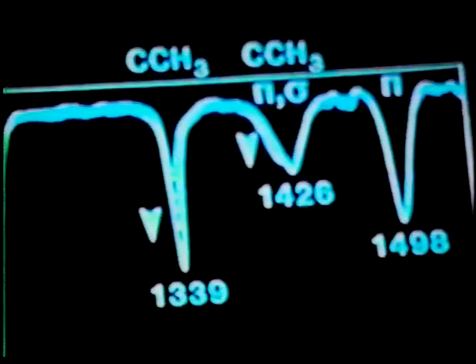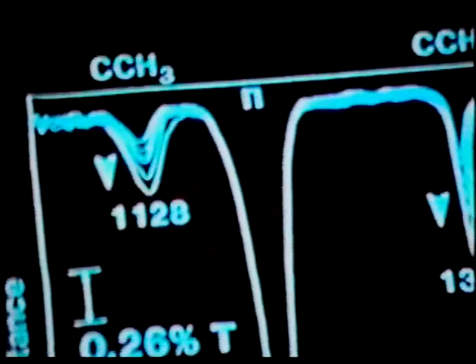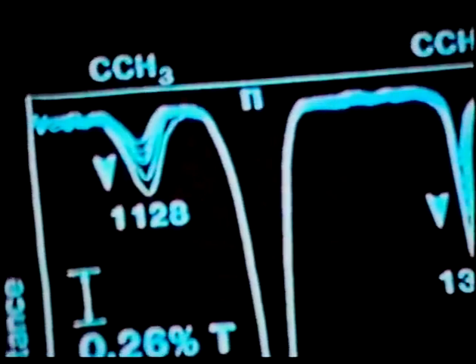Now what this suggests to us is that not only is it fine to be able to observe it, but we might be able to learn a little bit more about the nature of the interaction between the di-sigma bonded ethylene and the platinum substrate. And the most obvious thing that almost any chemist is going to want to do is make these measurements at a variety of temperatures and see if we can determine an activation energy.